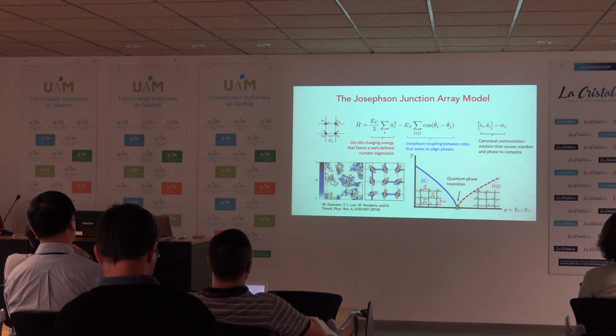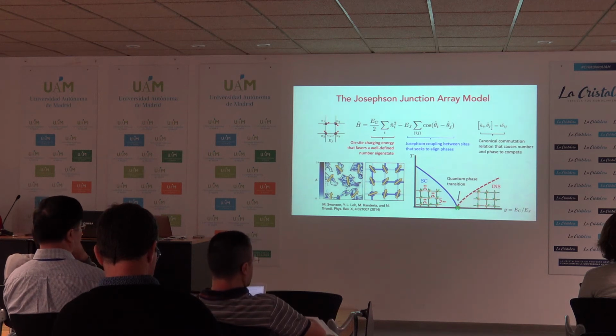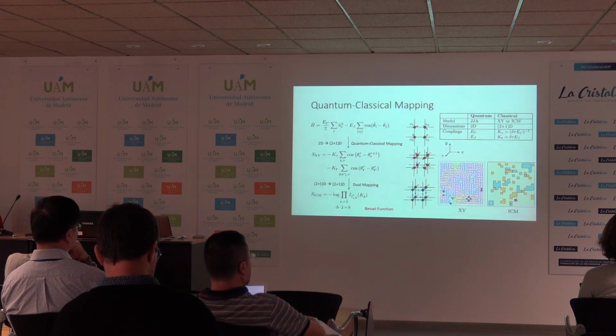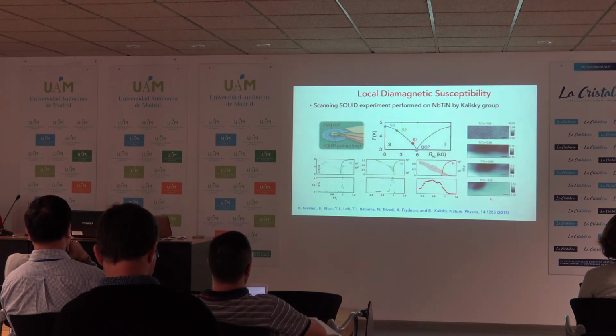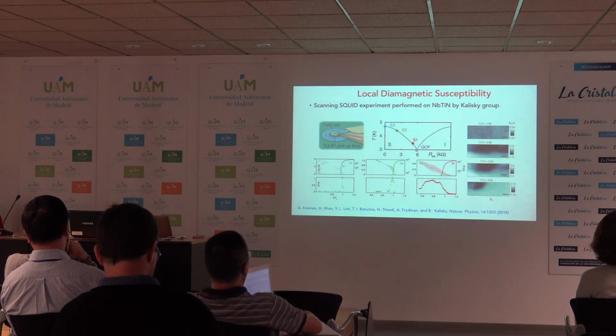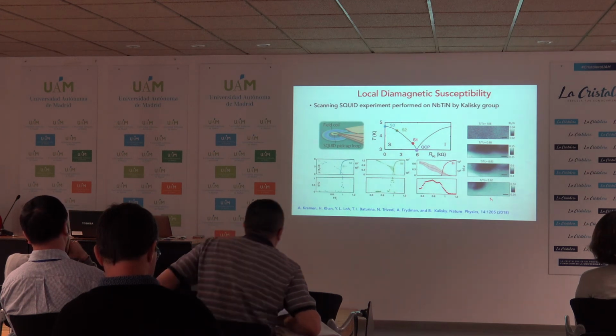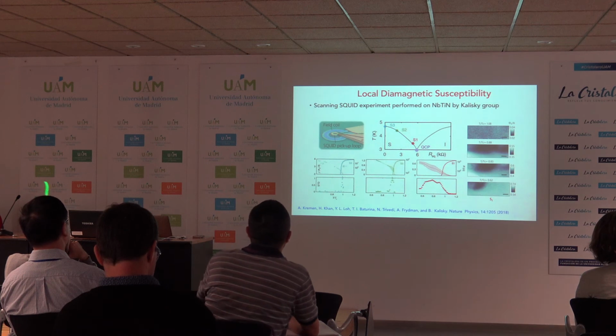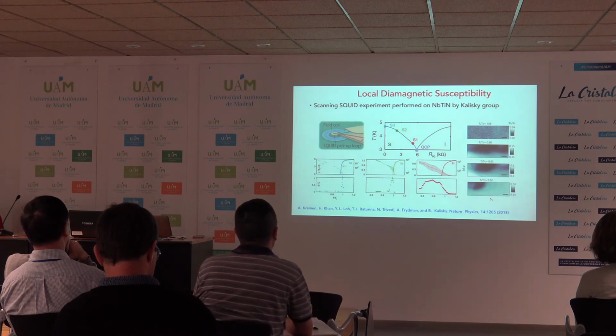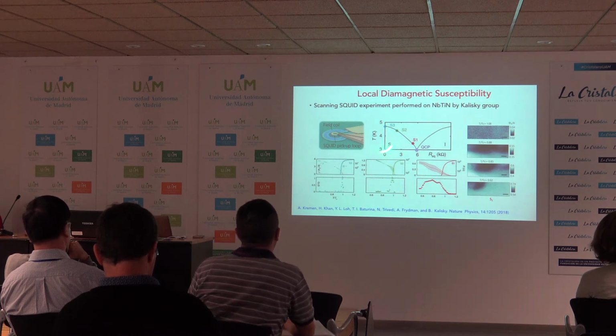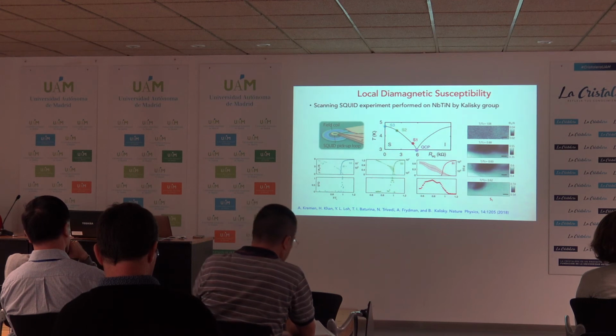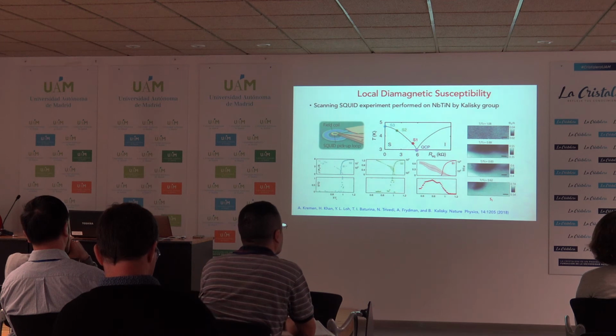So this model allows us to now look at much larger sizes because we have coarse-grained the model. And in particular, what it allows us to do is to look at these diamagnetic currents on a local scale. So this brings us to our recent collaboration with the Kalisky group, where they can use a scanning squid to measure now not on nanometer scales but on micron scales.